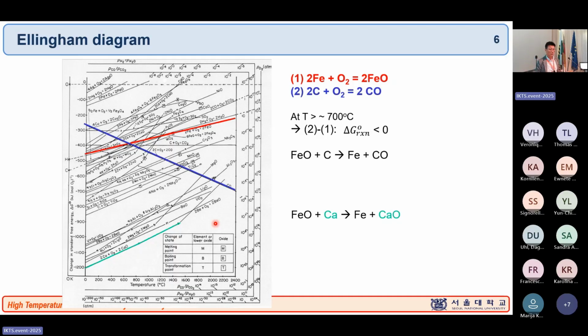And a lot of you, when you learned thermodynamics, probably learned this graph to obtain the equilibrium oxygen partial pressure. So for example, let's say here I have iron and oxygen becoming iron oxide. At the given temperature, if I want to know what oxygen partial pressure I need to make this reaction at equilibrium state, it means delta G of reaction equal to 0. Then you can draw a straight line from here through to that point, and you can read the partial pressure value here. That's the equilibrium. So that's basically the graphical solution of the previous mathematical solution.